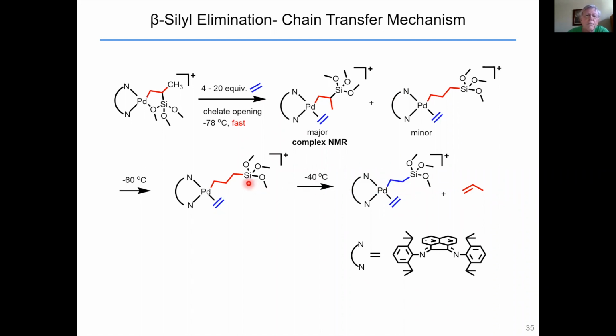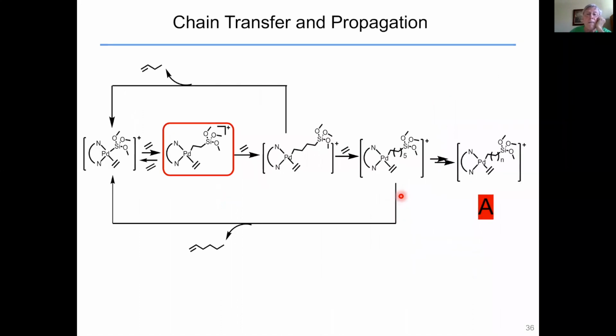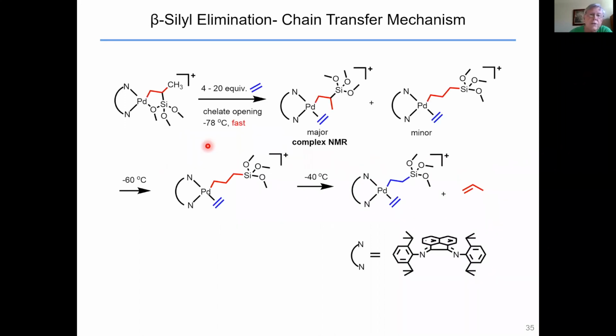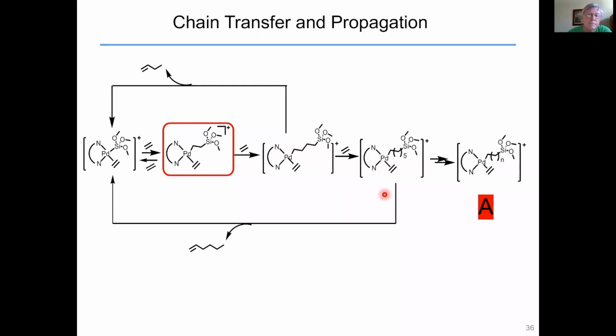So palladium must basically chain walk back to this species, beta-silyl eliminate to generate the propylene complex. Ethylene displaces propylene, just as in the previous case, nitrile displaced the propylene species. So imagine now we're here at this species I showed you on the previous slide, where we have a C2 linker in the ethylene complex. If this beta-silyl eliminates, and we're in the presence of excess ethylene, this simply traps back. So this gets us nowhere.